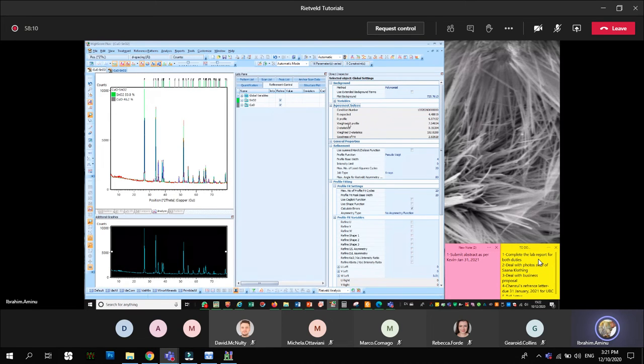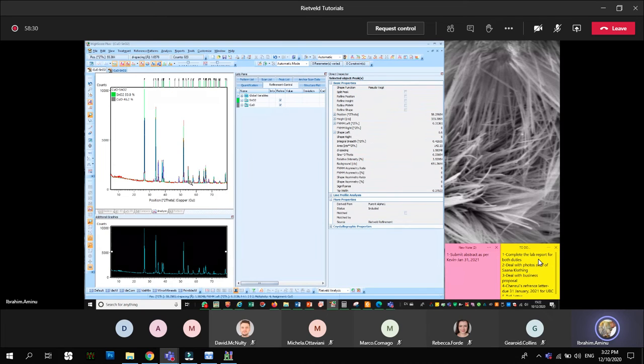So we see here the goodness of fit is 2.8. This is not great. This will help with your visualization. So here you can see it's not okay. Here the goodness of fit is also not okay. So this is a confirmation that your fit is not proper. Now you have seen that the tin has increased from 45 to 53, which is more than the copper, which was the opposite in the beginning. So this is also an indication that the fit is improving, but it's still not the best.